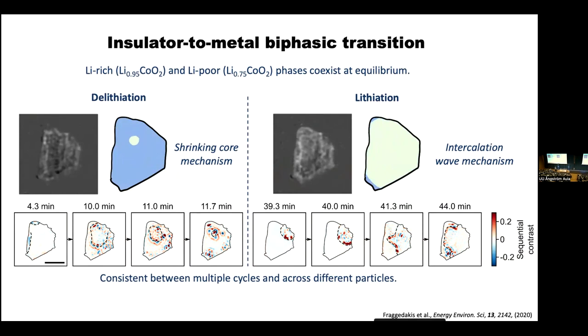So the shrinking core is one where you pull the lithiums out from the edge of the particle and the core gradually collapses in itself. So this is the metal insulator transition. It's a two-phase reaction. The other one on the way back is a different mechanism, and this is called the intercalation wave. And what happens here is that you have a nucleation event, in this case only one, on the edge of the particle, and the new phase grows across the particle. And so we can visualize this really beautifully.